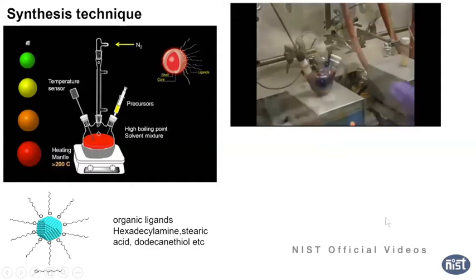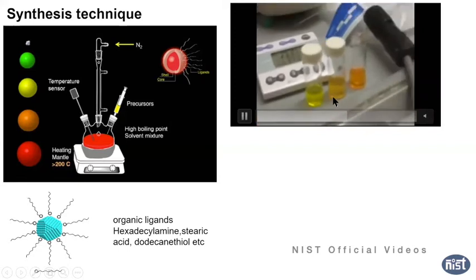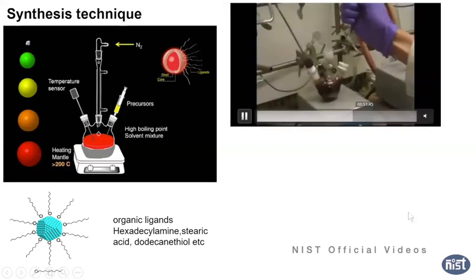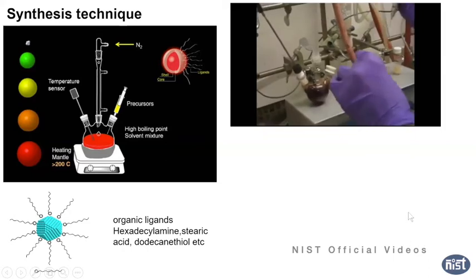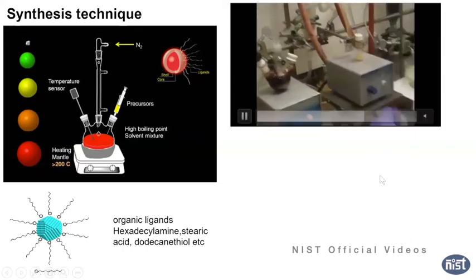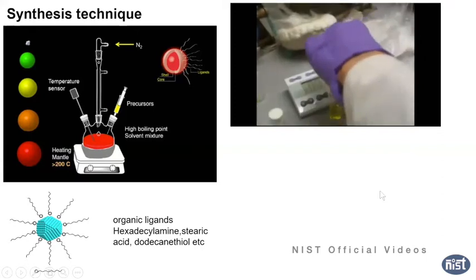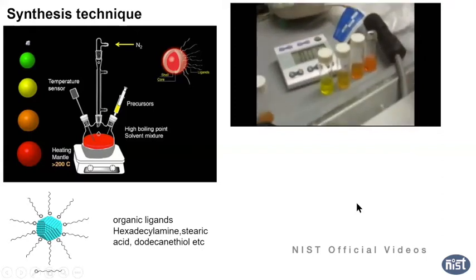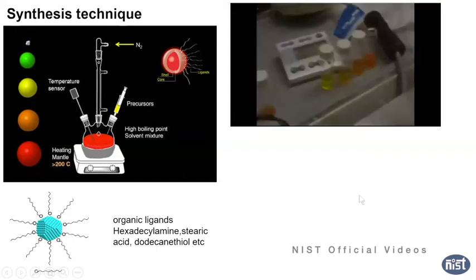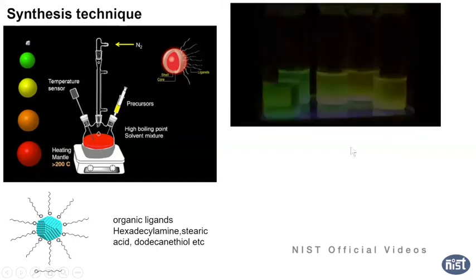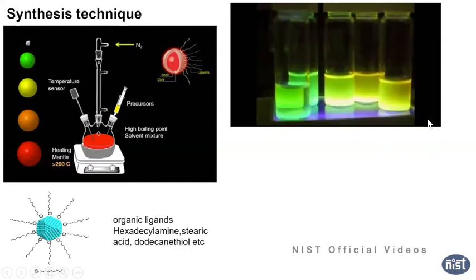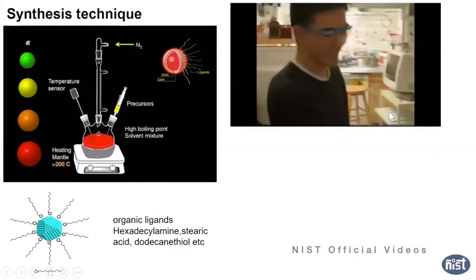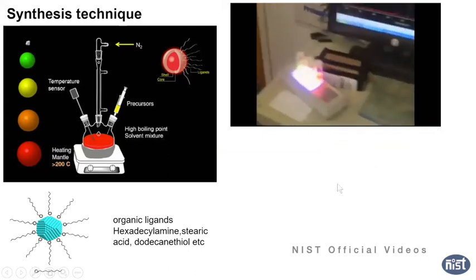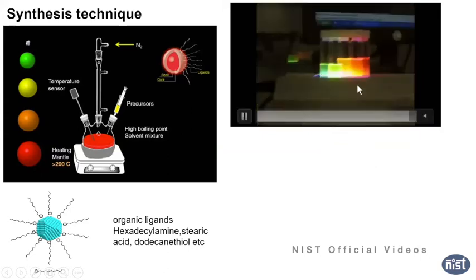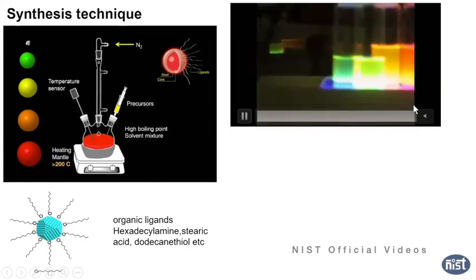But when it grows, it is different: three different colors, blue, green, and other. Under the UV lamp, it glows very well. Just at the end of the video, you can see it. When you shine the light on it, you see the green, yellow, and okay, we did not grow it in red. It's from one of our past labs, so I just added the video. You can see it's red. You can grow it up to more red, around 700 and 800 nanometers.